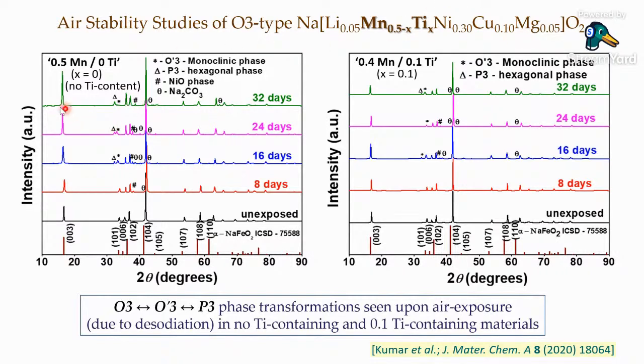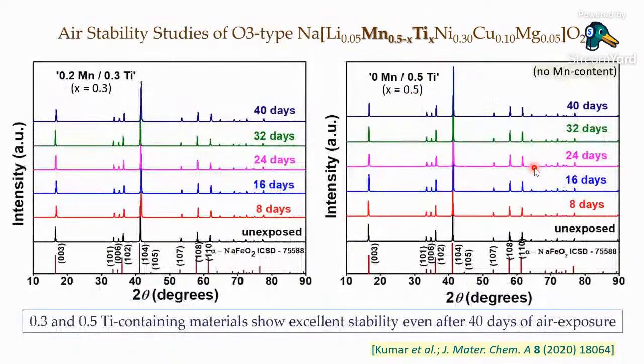Now, what we can see is, for the manganese containing composition with no titanium, the material is highly hygroscopic, and upon exposure to air for a few days, a lot of other phases start to form, and these phases actually form when sodium ion is taken out of the structure, which means that there is a spontaneous desodiation upon exposure to air for this material, especially when it had 0.5 manganese and no titanium. Now, with increase in titanium content, the rate at which the deterioration was taking place upon exposure to air got reduced, and when the titanium content was 0.3, and of course when it was 0.5, the material was fully air stable even up to 40 days. One can see no change in the XRD pattern upon exposure to air for 40 days.